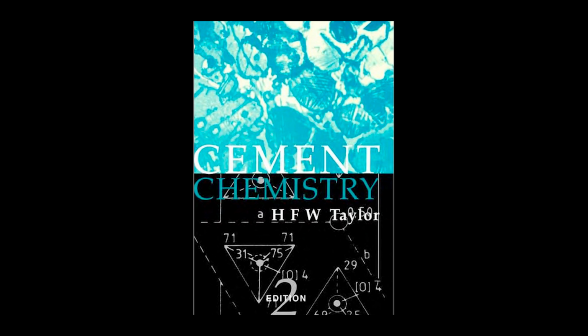Now, back to those reactive aluminates and ferrites. Their hydration, which is controlled by gypsum, produces the well-known AFT and AFM phases. That's right. In the initial phase, when gypsum is abundant, the aluminates and ferrites react to form ettringite, which is the AFT phase. This grows as these long, distinctive rod-like crystals. Then, as the sulfate supply from the gypsum is depleted, usually after the first few days, the ettringite becomes unstable and it reacts with any remaining aluminate to form monosulfate, the AFM phase.